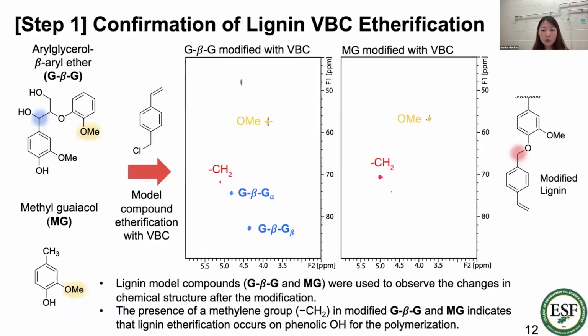So we used model compounds to confirm this VBC etherification. We used two types of model compounds: one has a beta-O-4 linkage and a phenolic hydroxyl group, called G-beta-G, and the other, called methyl guaiacol, has only a phenolic hydroxyl group. We put both model compounds through the same modification process using VBC. When we measured the 2D-HSQC for these model compounds, we observed that both types showed the methylene group, as shown for the BDO lignin and kraft lignin. It means that during the modification, a new methylene group is generated by connecting the VBC structure to the phenolic hydroxyl groups of lignin.